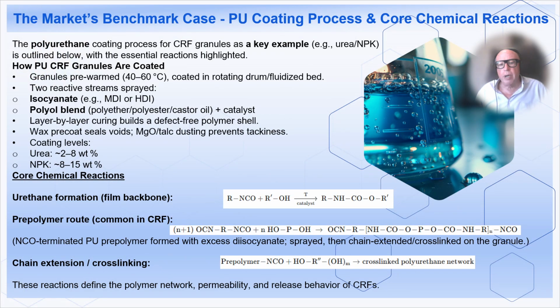The market's benchmark case, polyurethane coating process. Using polyurethane-coated fertilizers as an example, let's see how polymer-coated CRF granules are made. The process involves pre-warming granules to 40-60 degrees and coating them in rotating drums or fluidized beds using two reactive streams. The chemistry centers on urethane formation through the reaction of isocyanates with polyols, forming urethane linkages that create the polymer backbone.